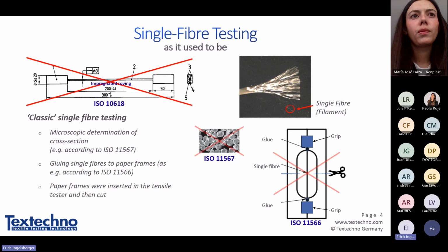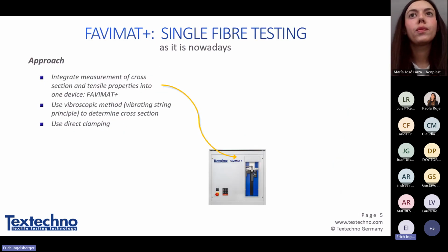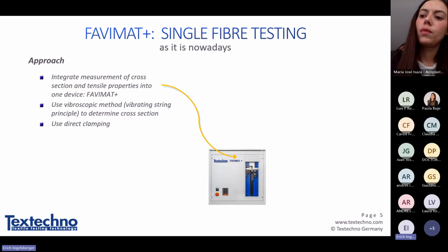We have found a solution to avoid this preparation of single fibers, and we can do this with our Favimat tester. The Favimat is a tensile tester for single fibers. With this instrument, by the way, we have entered the market, the composite industry, by only doing tensile tests of individual fibers.